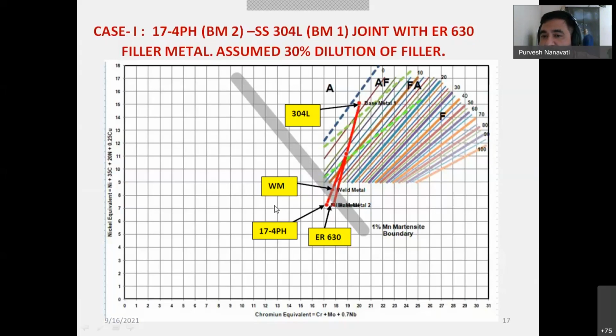So when your base metal is contributing 15% most of the time, 15 from this side, so 15 plus 15, 30, right? So assume 30% dilution. Now filler will be diluted by 30%. It means filler will contribute the rest of the amount. So filler will be 70% and 15 will come from either side of the base metal. So you may consider a point where you have your weld metal somewhere here, right? So your weld metal will be somewhere here, and that will fall in the region of the martensite boundary.